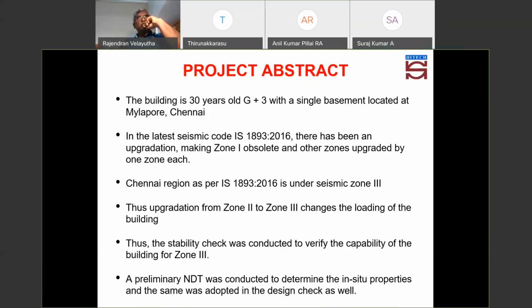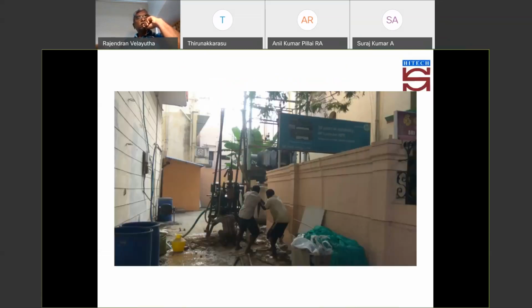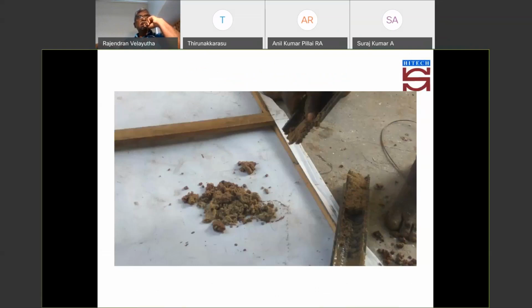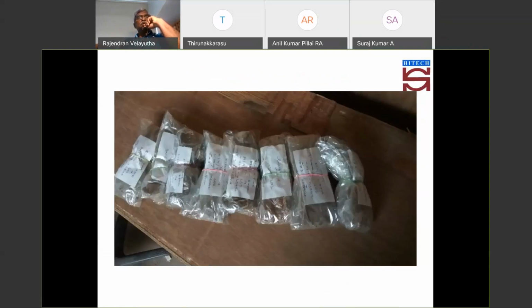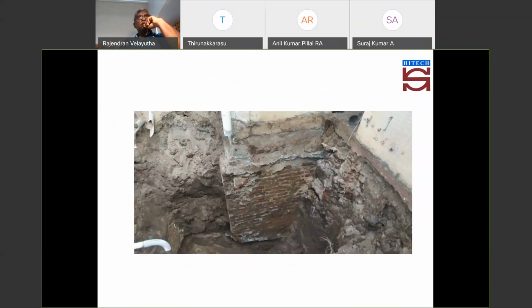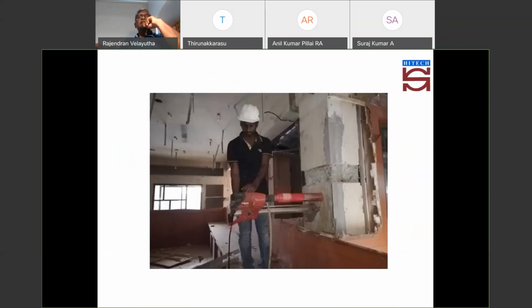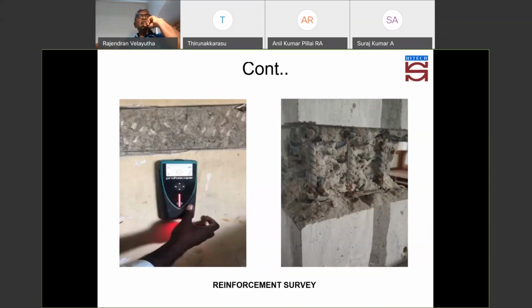So we have to do the GA drawing and then the profoscope survey. Of course, initially the survey has to be done, and testing has to be done for the soil. So we did a soil test, collected a sample, and determined the bearing capacity of the soil. And then it was a raft. We wanted to know the shoulder given out of this raft, and the net area available for the soil pressure calculation. We did the digging and found that out. Then of course, we did core extraction to get the fck value. We did the profoscope and profometer survey. As I said, at least at one or two places, you physically chip open and find out the actual diameter of the bar with a vernier, so that you can read it in combination with this.